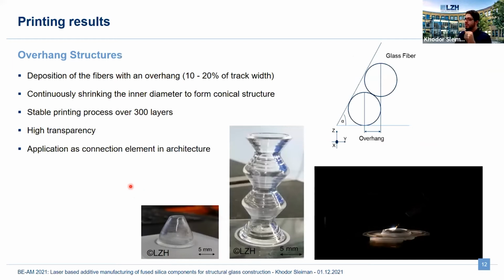Yeah, also we investigated the printing of overhang structures. You can see this here in the video and on the bottom, where we deposited the fibers with an overhang of 10 to 20% of the original track width. So we shrink the inner diameter continuously to form these conical structures. And then we did it the opposite to increase the inner diameter again. This process is quite stable for over 300 layers, what you can see here. The printing time was about 90 minutes, and it was still stable. You can also see the transparency of the structures.